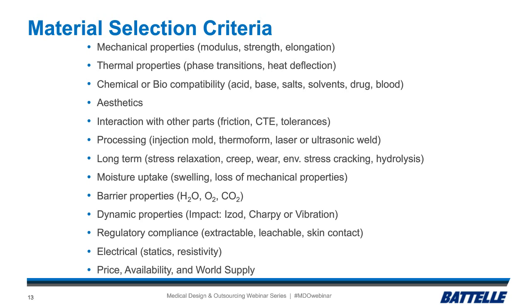Then think about things like moisture uptake. If you're using a nylon 6, it can take up to 6% of water out of just the ambient humidity. So you have to worry about swelling. You have to worry about loss of mechanical properties. It gets tougher, but the modulus drops when that happens. Barrier properties. Are you worried about oxidizing a product with oxygen? So you have to pick the right material so oxygen can't get through it. Dynamic properties, we had a slide on that already.